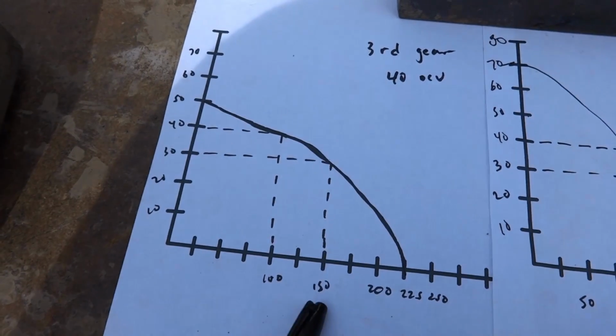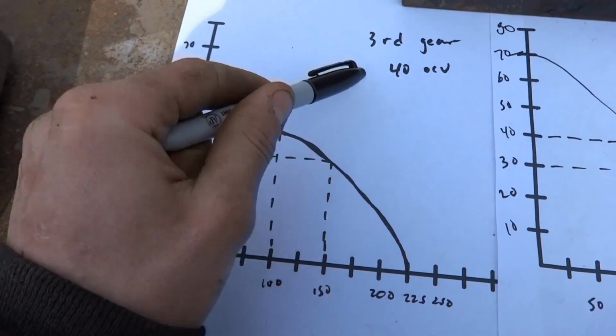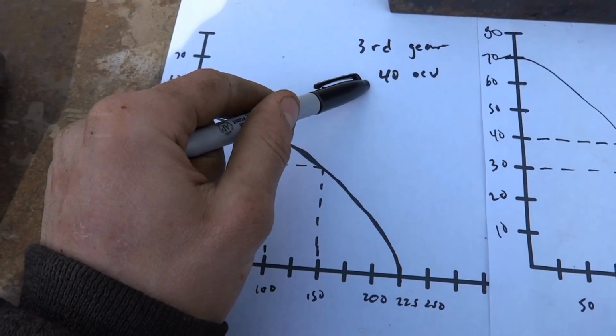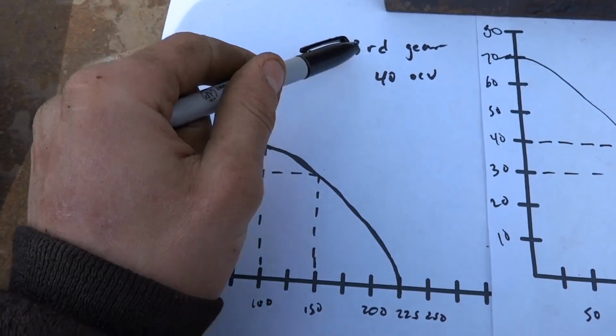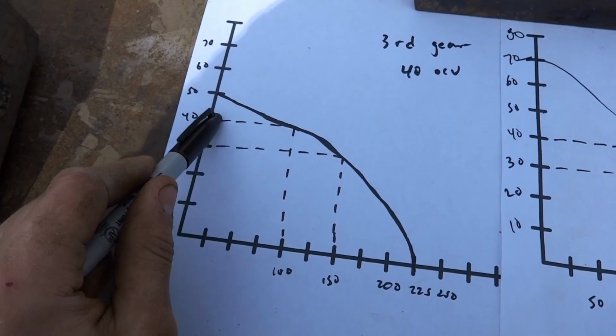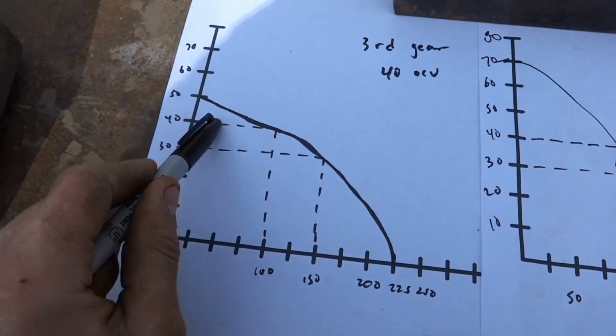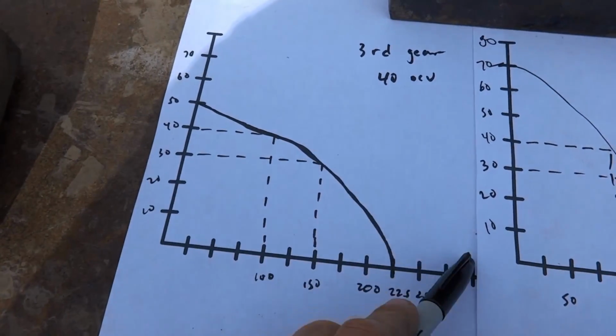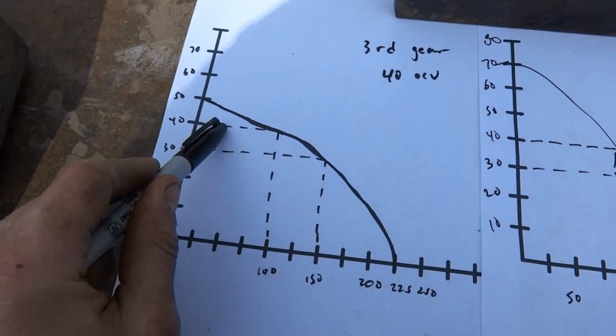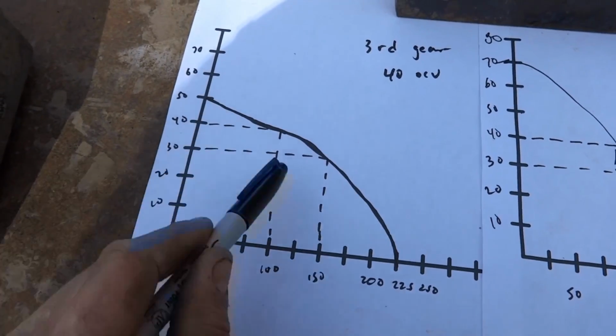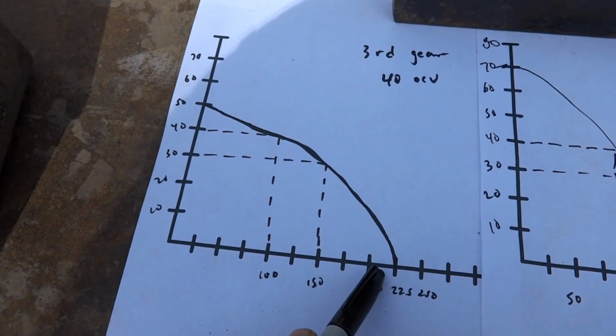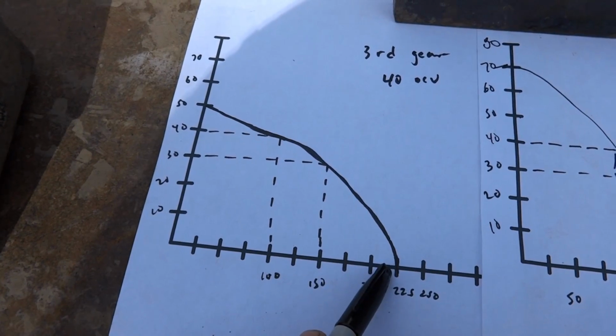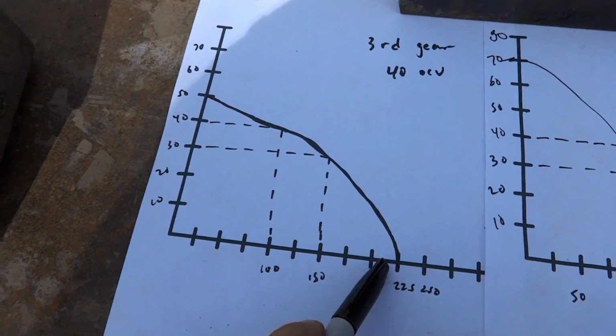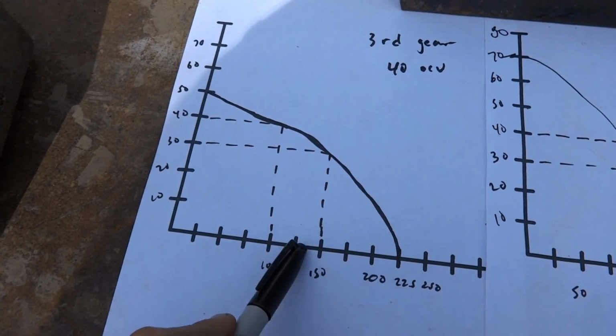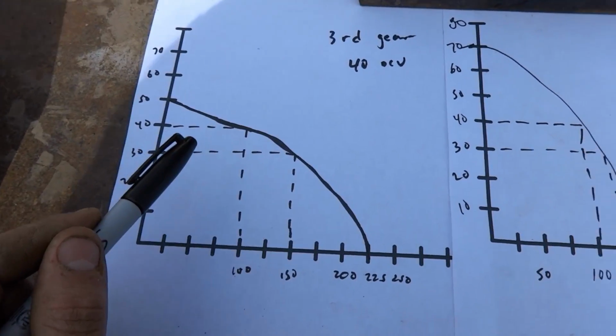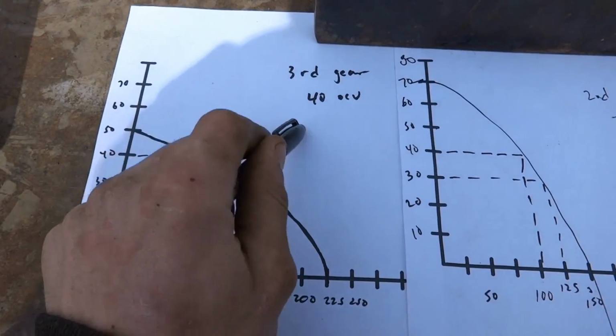If you notice how drastic the change is, this may be only third gear 40. You can imagine, say, fourth gear 40 or fifth gear 40, or even fourth gear 10 or fifth gear 10. You can imagine how low the voltage will be and the amperage, you see? Suddenly, you use arc length manipulation, you hold a tight arc in the side bevel there. Your amperage increases, your burn-off rate increases, your voltage drops off. You may go up a huge, significant amount of amperage. You give arc length across the middle to add voltage into the puddle, and your amperage may drop off quite significantly, and your voltage will increase. That is high amperage, low voltage.